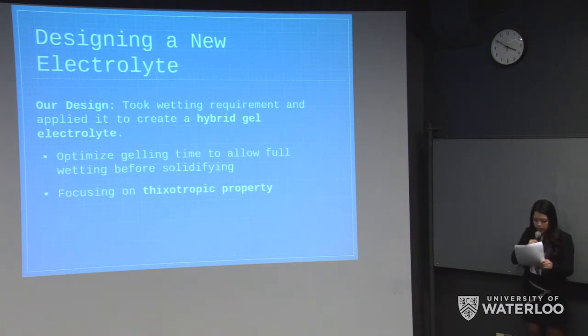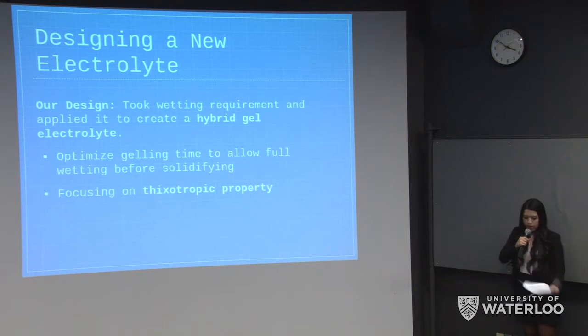So defining gelling time as the time it takes for an electrolyte to go from a liquid to a gel, we wanted to optimize the gelling time such that it was long enough for the full wetting of the separator, but not too long, so that even after wetting, it wouldn't continue to stay a liquid. So to achieve this, we decided to explore a property known as thixotropy.